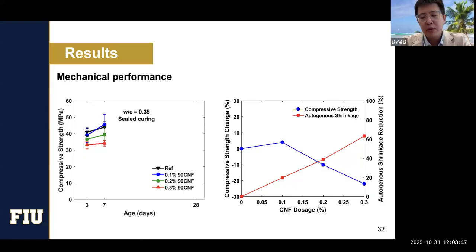But it could be one reason that we did not do any specific pre-dispersion process, because we just used a high shear force mixer. So we hope we can see more promising results to reflect the curve. Maybe we can add more, because for internal curing purposes, I think 0.1% might not be enough to completely remove the shrinkage, but we'll be able to see some decrease as well.